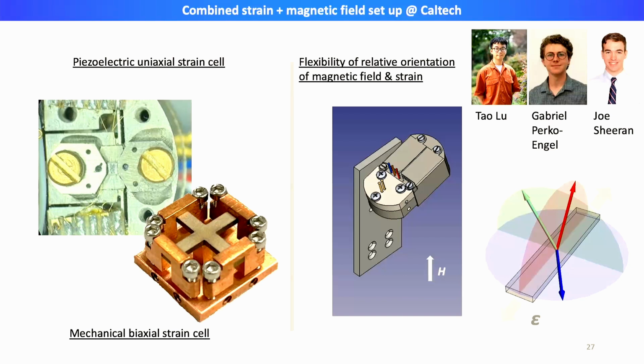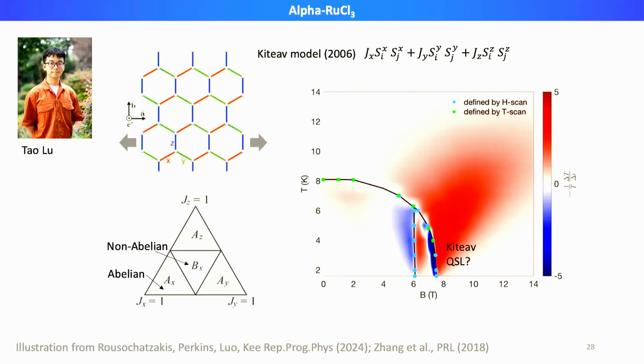And the part I'm showing you on the right is perhaps more for the experimentalists in the audience. In our lab, we have vertical magnetic fields up to 14 Tesla, which is a very strong magnetic field. And we try to set up our strain cells such that the direction of the magnetic field can be rotated within the three different planes that we're showing here, with respect to the direction you're deforming the material. So we are not able to achieve this in a continuous manner, but at least we are able to do this in a discrete way and access quite a bit of combination of the relative orientation of strain and magnetic fields.